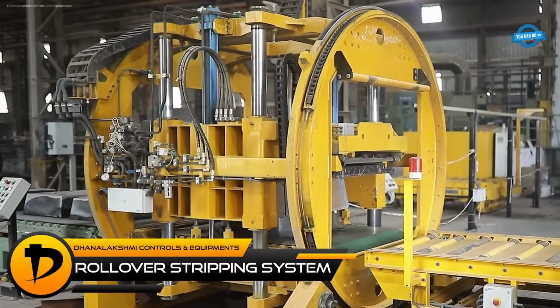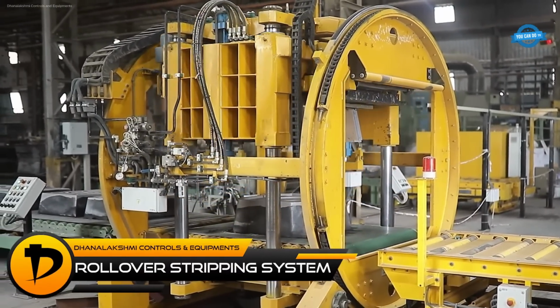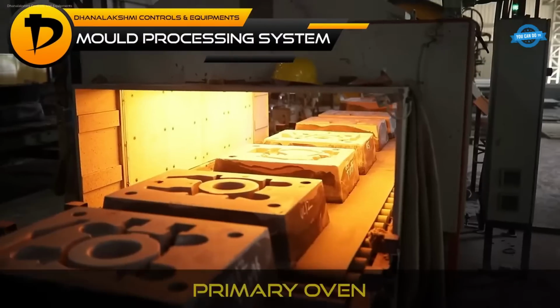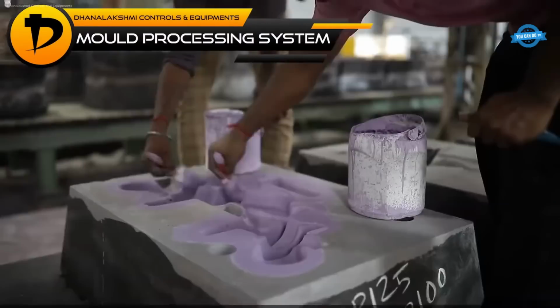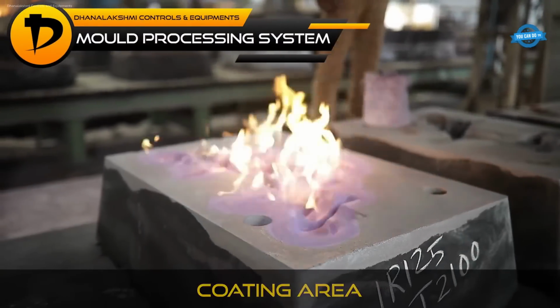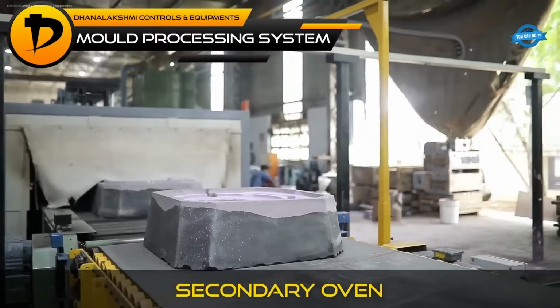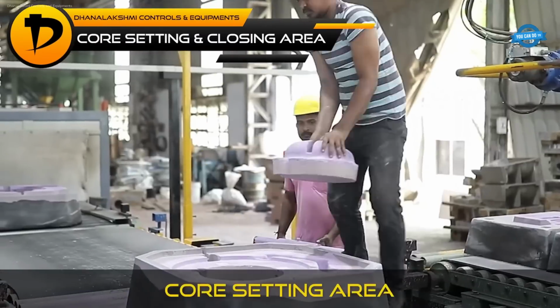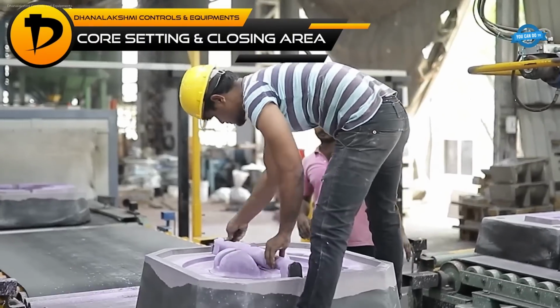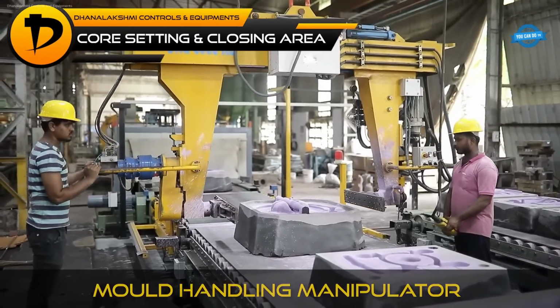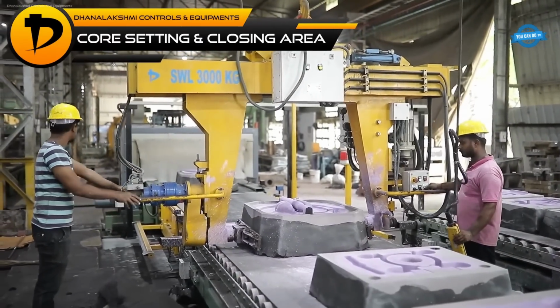Molds enter the primary oven for initial sand curing, followed by the coating area, where refractory coatings are applied to enhance surface finish and resist thermal shock. They then pass through a secondary oven for final curing before moving to the core setting and closing area. Here, mold handling manipulators assist in precise core placement and secure mold closure.